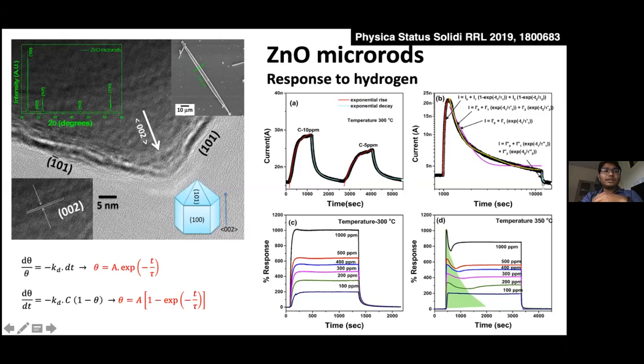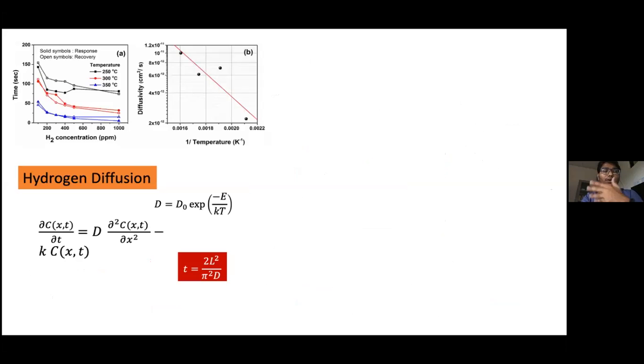Okay, so then we were looking into what could be the reason for this, and started reading lots of papers wherein people said hydrogen, being a smaller gas, when adsorbed on the surface, can readily diffuse into the lattice. Once it diffuses into the lattice, it can actually become some kind of a defect inside the lattice. Now it is an interstitial hydrogen defect. Okay, now where will it go?